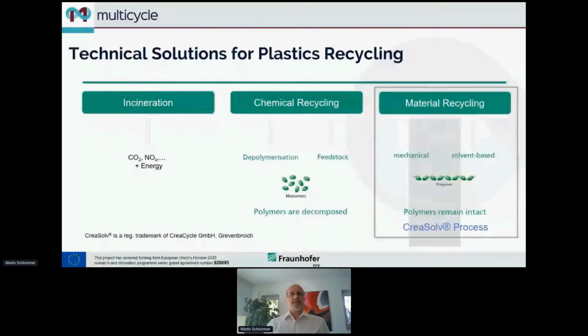The other idea is, of course, chemical recycling. Here we have more or less two ideas. The one is depolymerization, which may be useful for polyamides, or we have a kind of pyrolysis, thermolysis, which is a feedstock recycling. Both have in common that in the end, if you go back to polymers, you have to start from feedstock or from monomers. You go very, very far back in the value chain to get something which can then be recomposed to polymers.